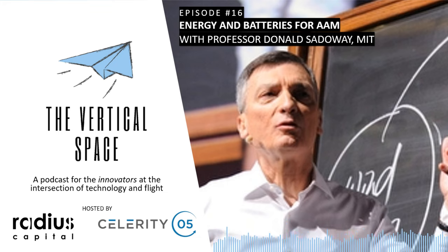And as far as lithium sulfur goes, it's advantageous because it's much lower cost. Sulfur is a lot cheaper than cobalt oxide, and it's more readily available. But no one's been able to make it work properly because the sulfur is sparingly soluble in the electrolyte. Then you end up with these multiple valences of sulfur that lead to parasitic side reactions. They call it redox looping.